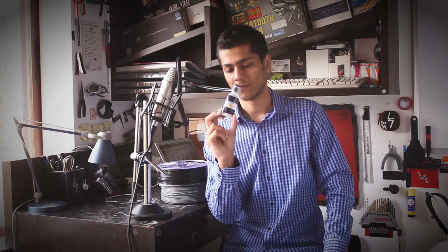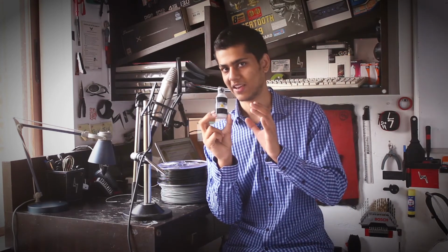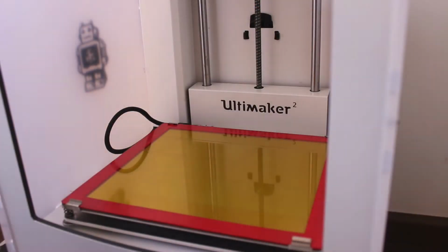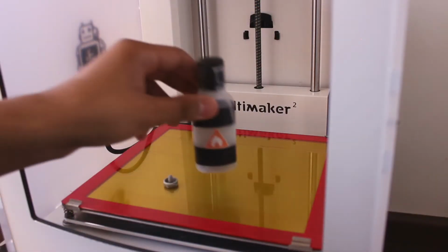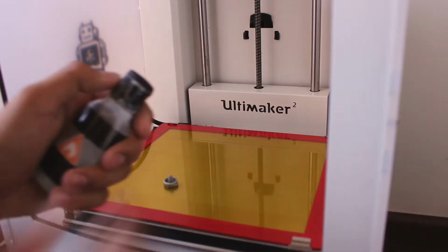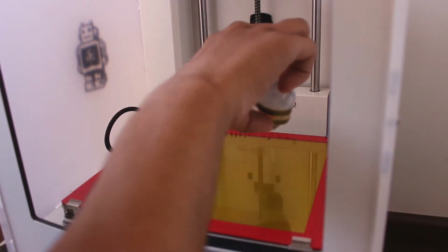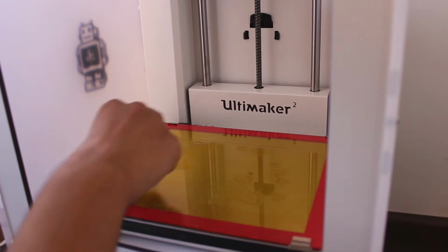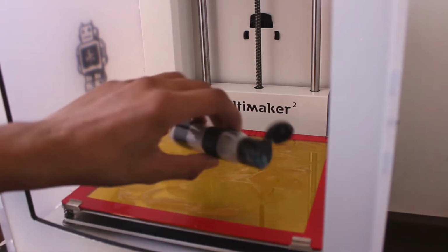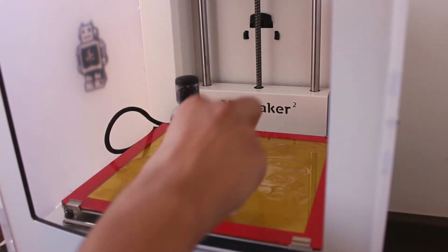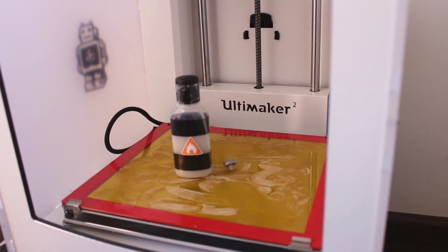What I do use is this. This is a mixture of acetone and ABS. We call this ABS slurry. ABS basically dissolves in acetone, and you get this mixture. You basically pour this mixture on a glass bed, and then you will have perfect adhesion, because the mixture sticks with ABS just amazingly. You get amazing adhesion and almost no shrinkage. If you have proper flow of the ABS slurry on the bed, you will not notice anything.